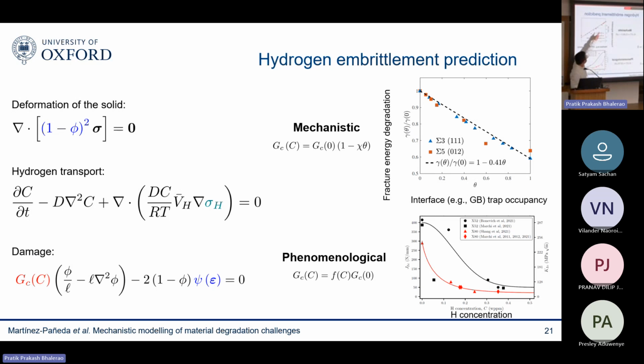And then you do atomistic simulations. These are DFT calculations for two types of grain boundaries in nickel. And then you can come in here with your grain boundary occupancy, and you can directly quantify the reduction in fracture energy or surface energy for that particular hydrogen concentration. So in that sense, you don't have to fit anything. There's no calibration involved. You just need to do one atomistic calculation once in your lifetime, offline, and that's all you need. So this is the more mechanistic approach. Often, working with industry, they tell us they don't trust atomistic calculations.